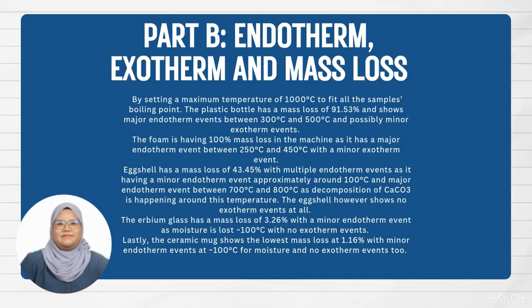Now we move on to the ceramic samples. The eggshell has a mass loss of 43.45% with multiple endotherm events as it has a minor endotherm event approximately around 100 degrees Celsius and major endotherm event between 700 degrees Celsius and 800 degrees Celsius, as decomposition of CaCO3 is happening around this temperature. This eggshell, however, shows no exotherm events at all. The erbium glass has a mass loss of 3.26% with a minor endotherm event, as moisture is lost approximately 100 degrees Celsius, with no exotherm event. Lastly, the ceramic mug shows the lowest mass loss at 1.16% with minor endotherm event at approximately 100 degrees Celsius for moisture and no exotherm events too.